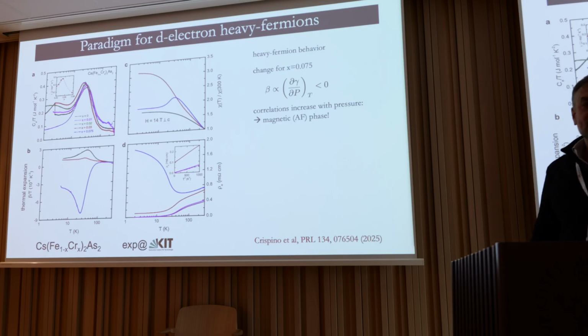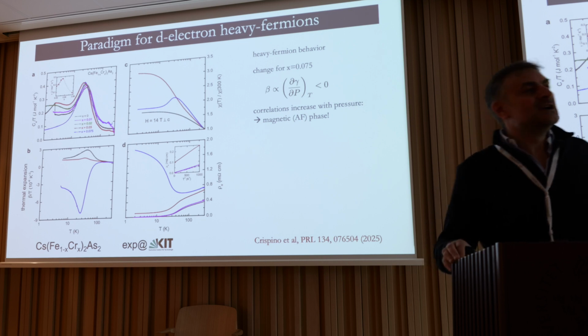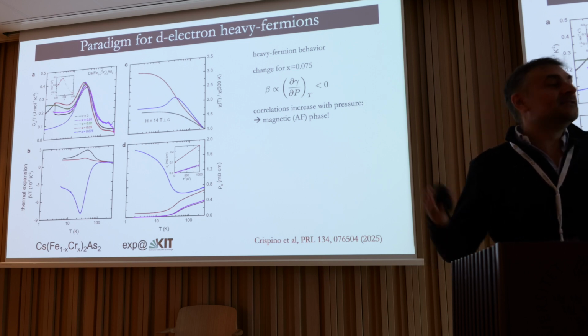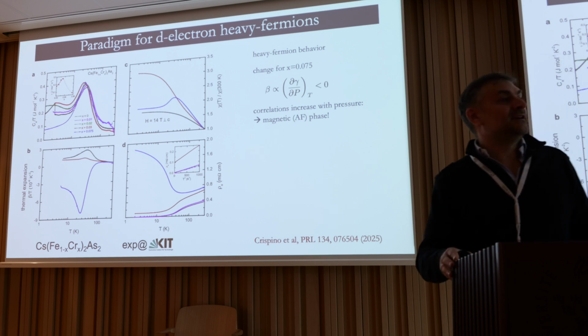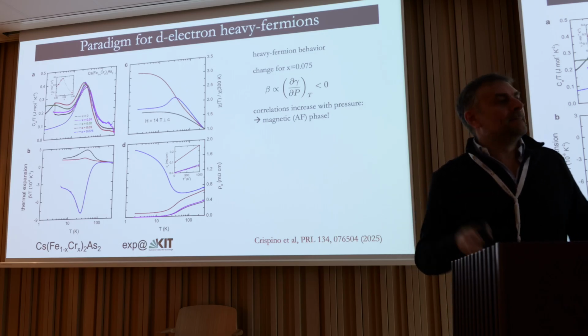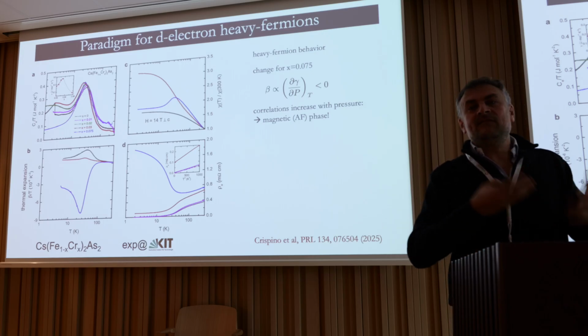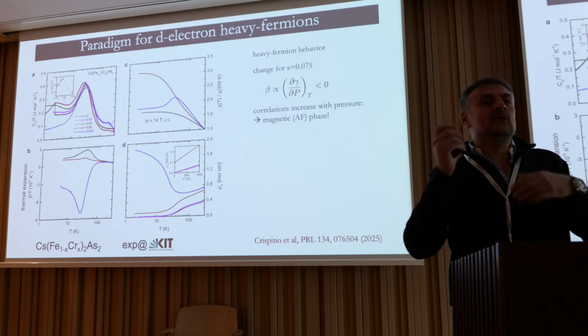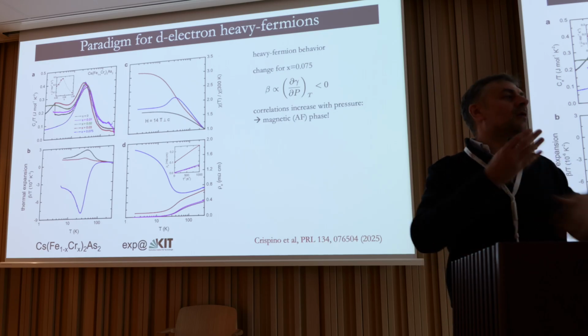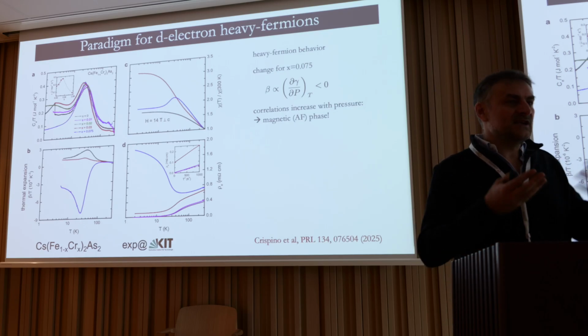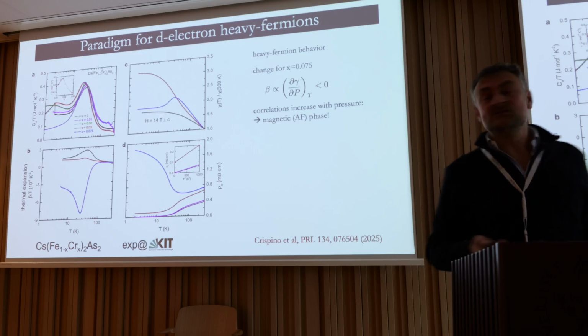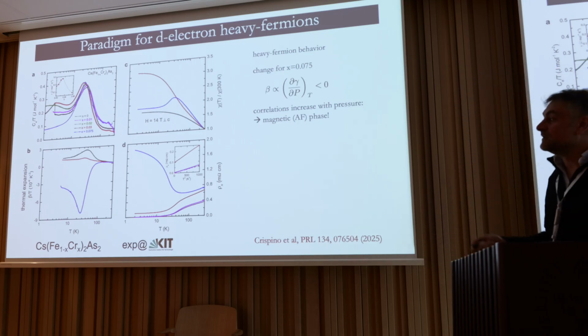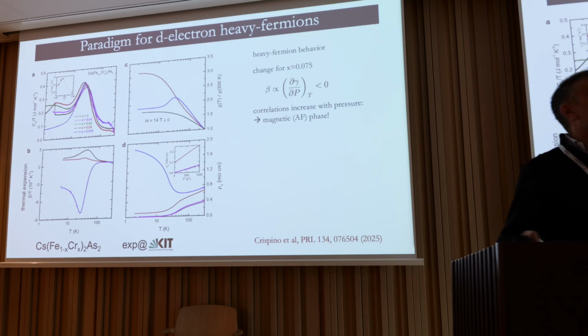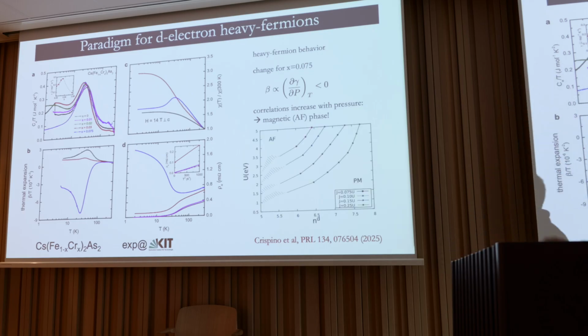Here you have the opposite, and there is one phase in which this typically happens: the antiferromagnetic phase, or a magnetic phase in general. If you apply pressure, you decrease the effect of interactions, you reduce the magnetic moment, and you induce more paramagnetic fluctuations, which increases the correlation. So this is another confirmation that in this compound you enter an antiferromagnetic phase that basically kills the heavy fermionic behavior.